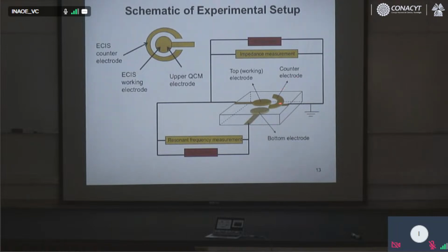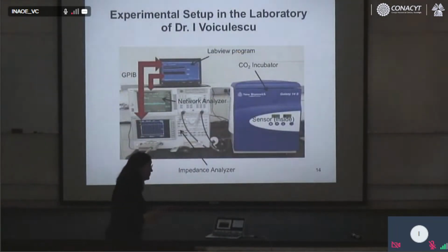So for the impedance measurement, you need an impedance analyzer to connect the 2 electrodes. And for the resonant frequency of the quartz crystal microbalance, you need a network analyzer. So you need these 2 devices. And here you can see the upper QCM electrode, which is also the working electrode for the impedance spectroscopy, and the counter electrode here. And I also show you a picture from my lab.